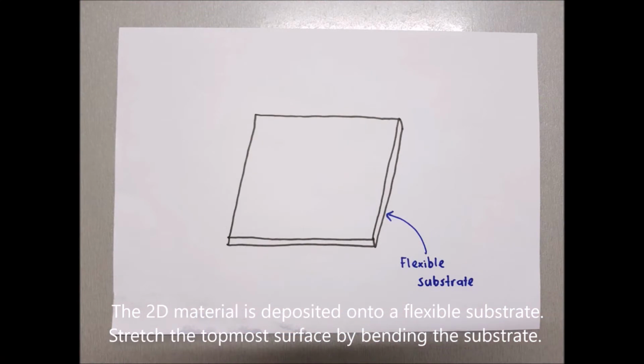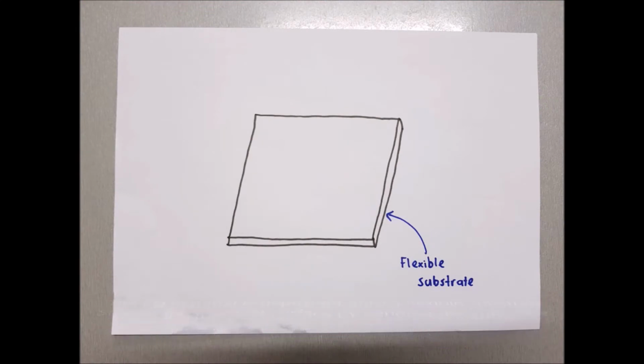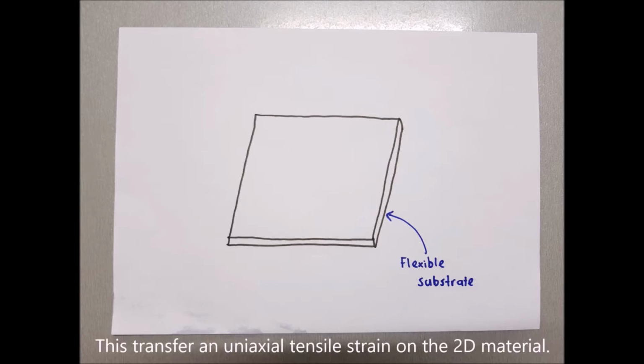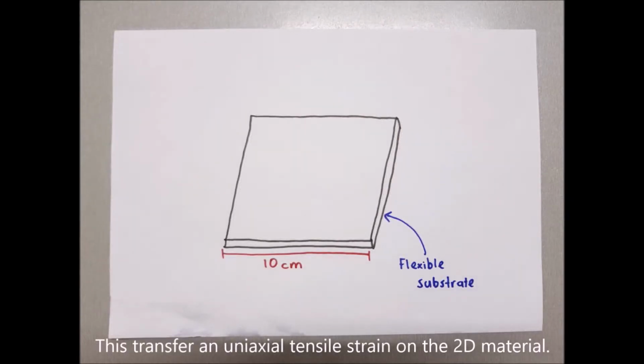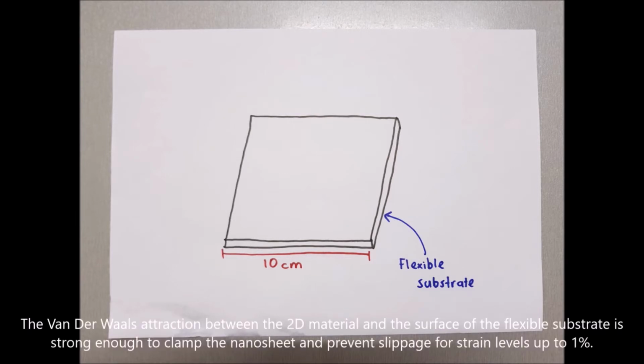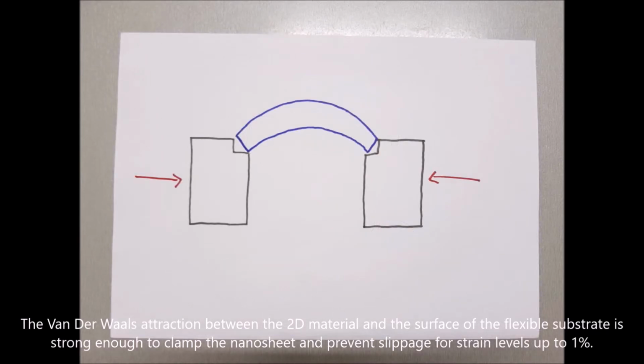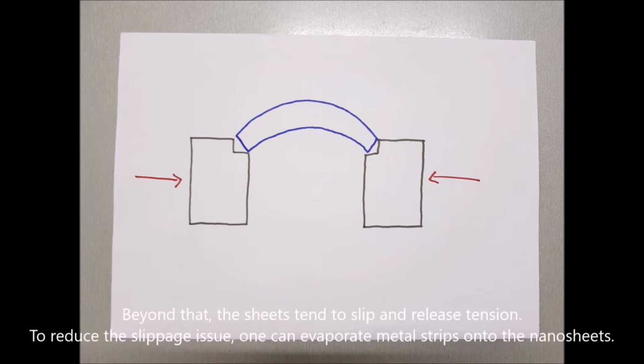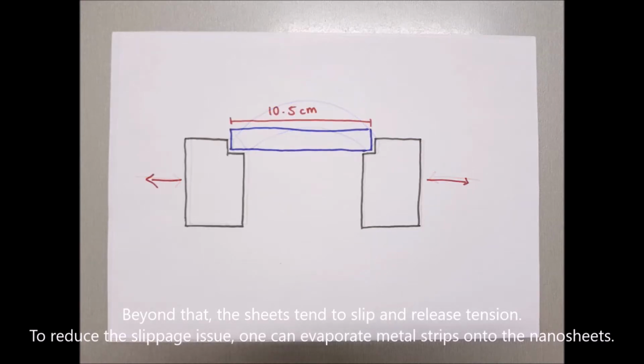The 2D material is deposited onto a flexible substrate. Stretch the topmost surface by bending the substrate. This transfers a uniaxial tensile strain onto the 2D material. The van der Waals attraction between the 2D material and the surface of the flexible substrate is strong enough to clamp the nanosheet and prevent slippage for strain levels up to 1%. Beyond that, sheets tend to slip and release tension. To reduce the slippage issue, one can evaporate metal strips onto the nanosheet. These act as clamping points.